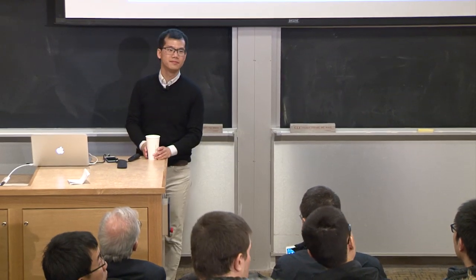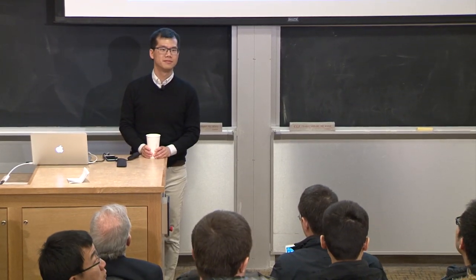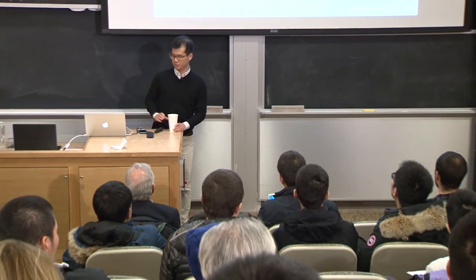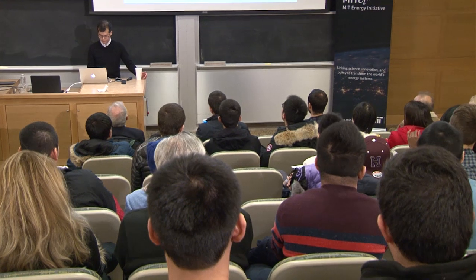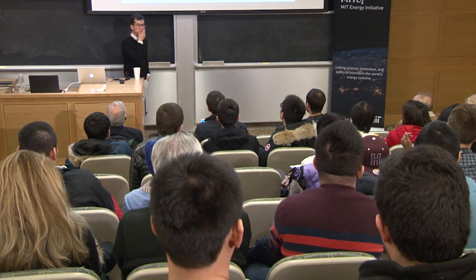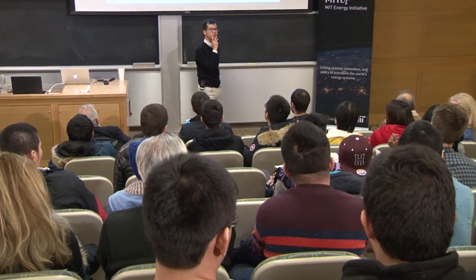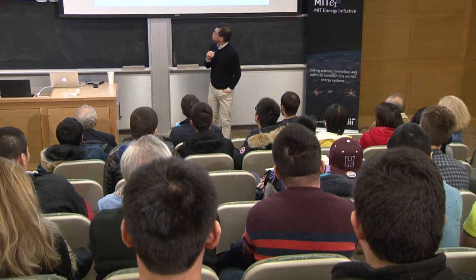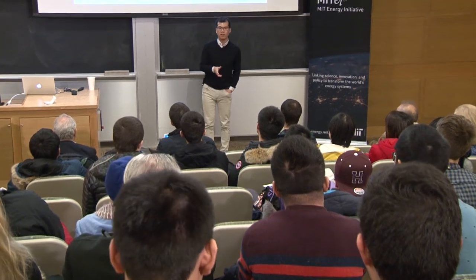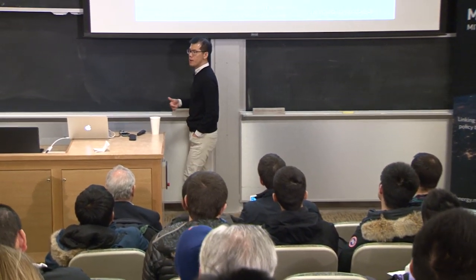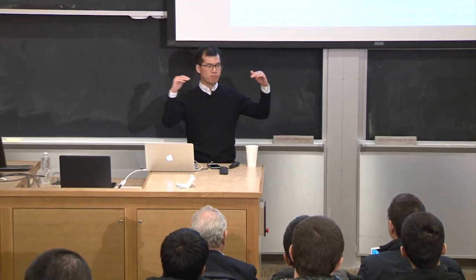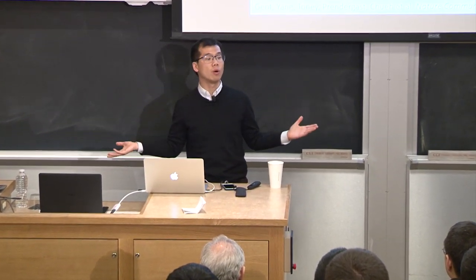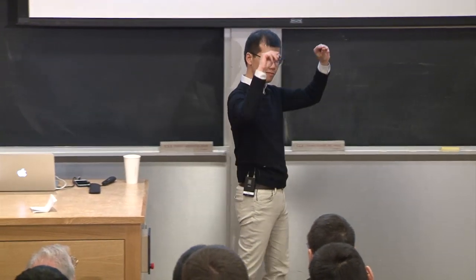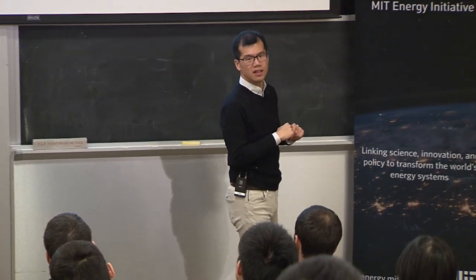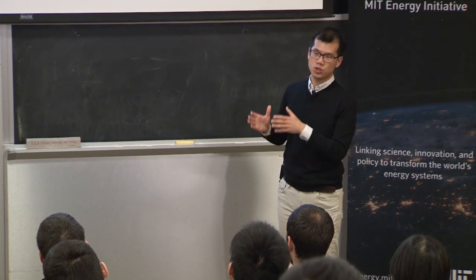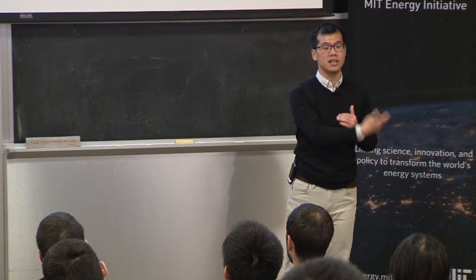You mentioned being able to reduce or prevent structural rearrangements during lithium intercalation. Could you mention other ways of doing that besides overstuffing with lithium? Maybe I just missed the other methods. Yeah, so there are many ways to avoid the rearrangement. People have thought of, for example, putting additional atoms in the layer, something that doesn't go away, like aluminum, to keep the layer open. So that's one strategy. But largely the structural rearrangement happens in concert with the oxidation of the atoms.